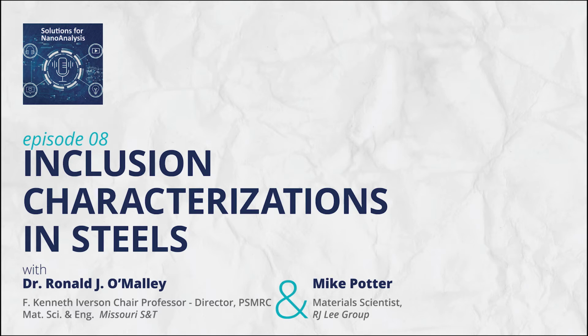So with all that, we use deoxidants to tie up the oxygen and generate these oxides. And one of the things that we need to understand is, what do these oxides look like? What are their shape, their size, distribution, their composition? How do they evolve over time in the steelmaking process? And this is where the technology that we're talking about today actually comes into play, because we can sample these steels at various stages in the process, take solid sample pucks from the liquid steel at different stages, grind them and polish them, and then look at them under the SEM and actually characterize those inclusions.